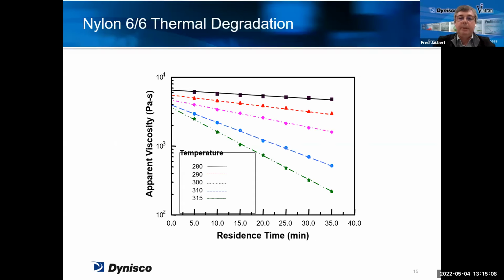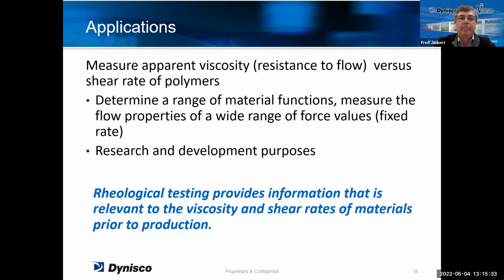This is, for example, what we can see. This test has been run on a nylon 6.6, running every time for 35 minutes at various temperatures, from 280 to 315. And we see obviously that the higher the temperature, of course, the faster the degradation of the product.